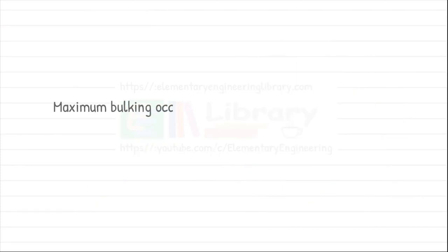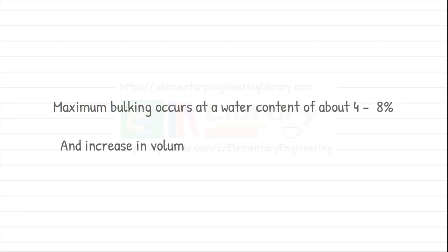The maximum bulking occurs at a water content of about 4 to 8 percent. An increase in volume of sand may range from 20 to 40 percent.